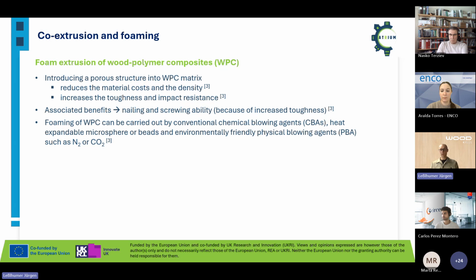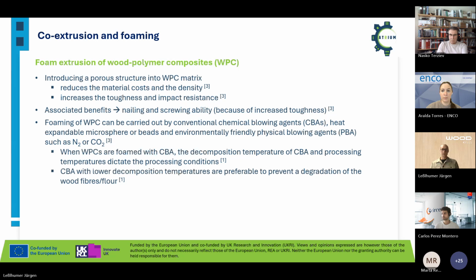And this foaming can be done by chemical blowing, by adding a chemical blowing agent, by adding a physical blowing agent, or you can also use heat expanded microspheres or beads. Yeah, and when these WPCs are foamed with chemical blowing agents, the decomposition temperature of these chemical blowing agents dictates the temperatures. So when, for example, these chemical blowing agents decompose at 190 degrees, we have to use a melt temperature which is higher than this temperature. But in this case, we also have to look at the melt temperature, because the limit for WPC to avoid the degradation of the natural fibers is 200 degrees, so the decomposition temperature of the used additives must be below this temperature.